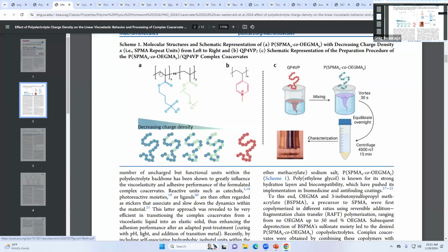So these guys use that. They're going to make these anionic polymers that way, and then they're going to put in salt. The problem is that they're liquidy when they don't bond, and they don't bond when you put in enough salt to screen the charges. So it's going to be a concentrated salt solution of these anionic and cationic polymers mixed together. And once it goes into your blood, which has a much lower salinity, there's less screening. So then the charges can start bonding, and it makes a glue, a pressure-sensitive adhesive.